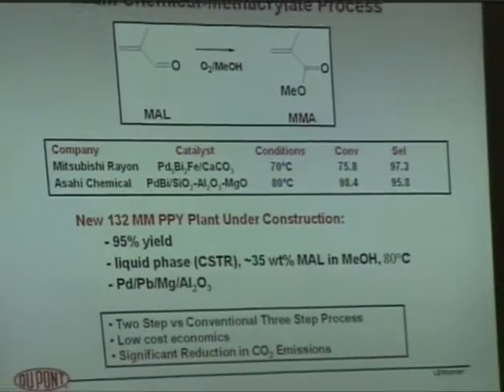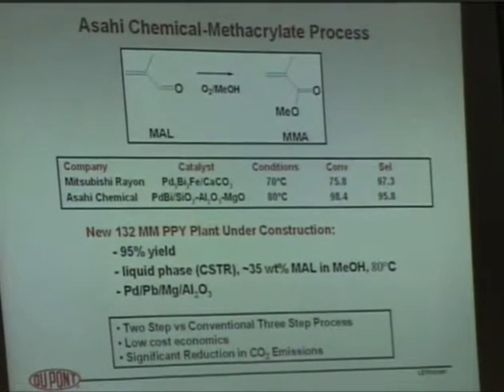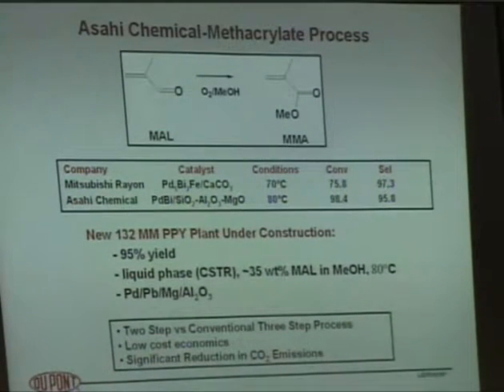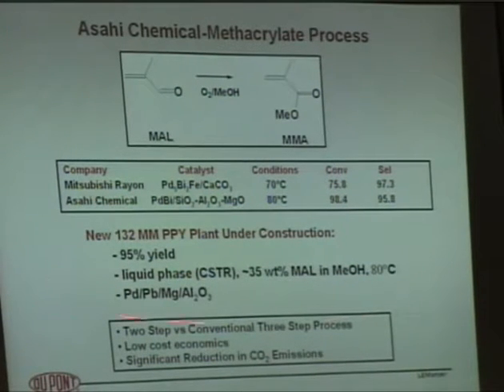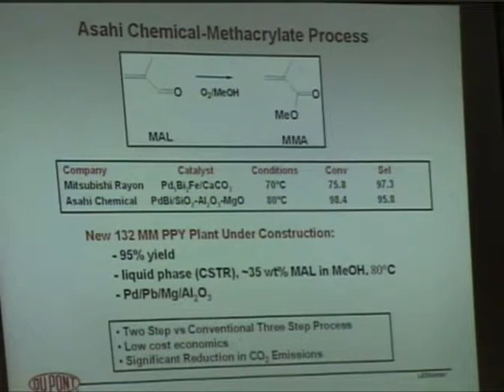So the overall process has a much higher yield, over 90% overall yield compared to 75%, significant reduction in the amount of carbon dioxide that's generated in the process. They operate at 80 degrees centigrade instead of 350 degrees centigrade in that second step, and it looks like this is the way to go to make methyl methacrylate in the future. So fine job in that area.